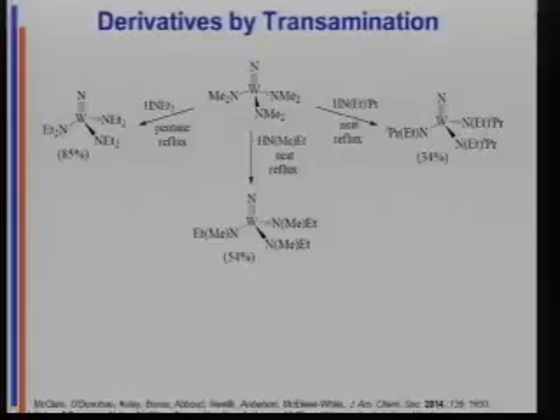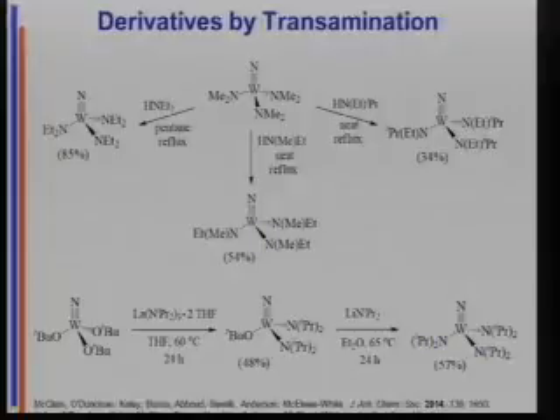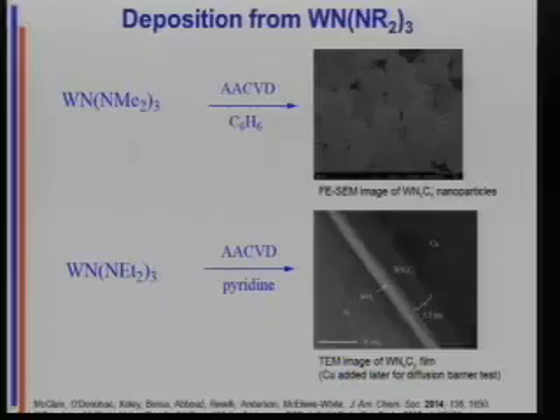We made about 24 of them now, including the really hindered tris diisopropyl one, which has to be done a little different way, but we can get hold of all of these. And so then we did depositions, okay? And it turns out that you can take this one, this is the methyl one, and you can deposit nanoparticles at low temperatures. And at slightly higher temperatures, you can deposit films. This is a high resolution TEM of a 5 nanometer film that passes the diffusion barrier test.